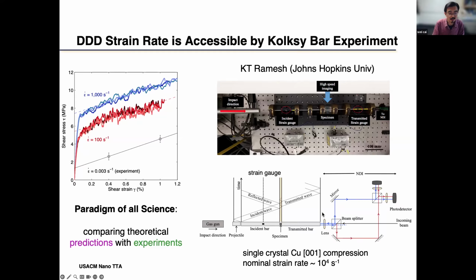Anyway, maybe we exaggerated how hard it is for us to go to low strain rate. So he went ahead and did the experiment at 10 to the 4 per second, even though we can handle 10 to the 3rd or even 10 to the 2. But 10 to the 4 is no problem. Also, the higher the strain rate, the easier for the simulation. So we try to have this one-to-one comparison between experiments and DD simulation at this high strain rate.